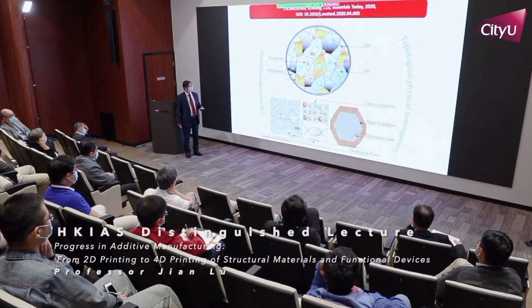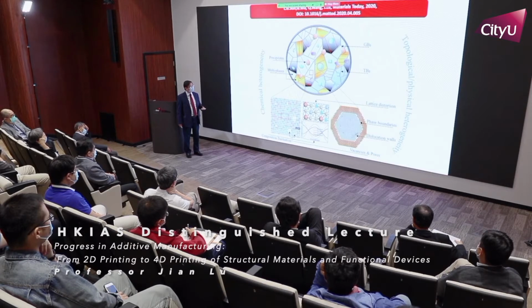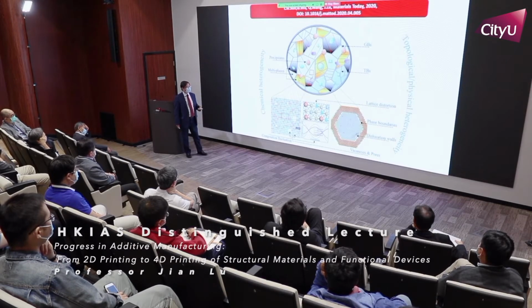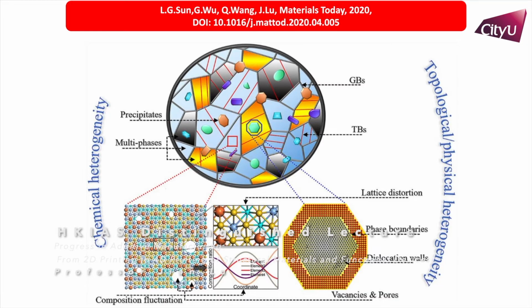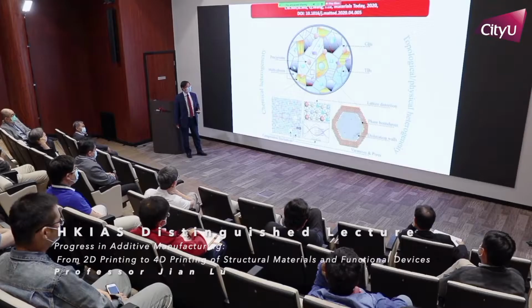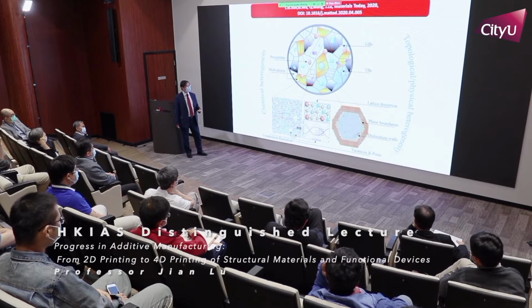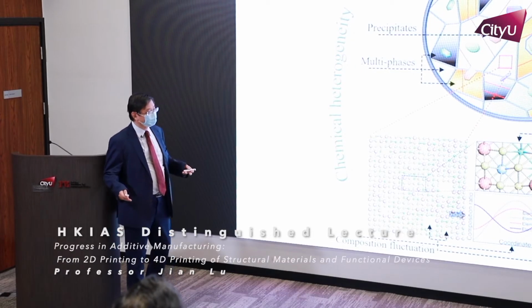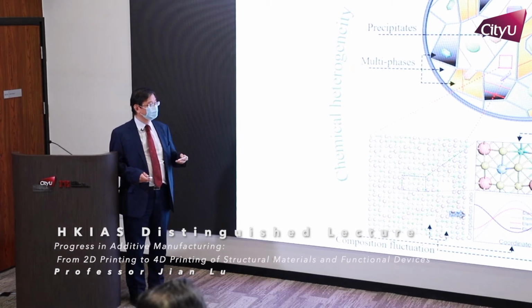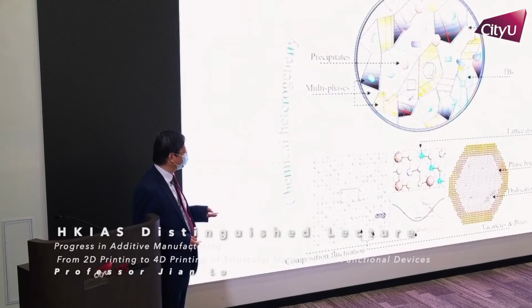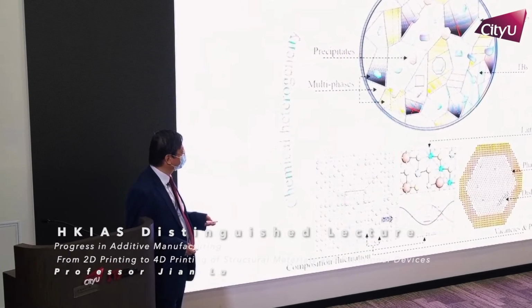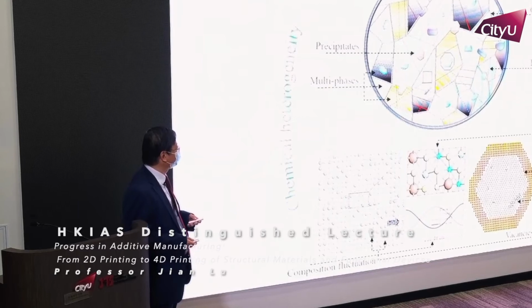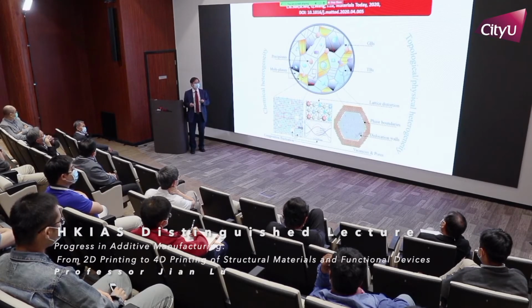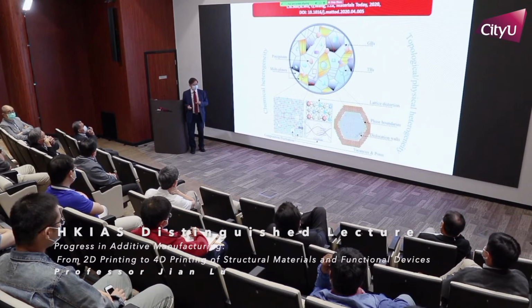So when you insert different material with different atomic size, then locally you generate a lattice distortion for a normal structural material. Of course, we can also have other defects such as vacancy, pores, dislocation, phase boundary. All these can be managed. So we can say today with different tools, manufacturing tools, material processing tools, we can try to manage and organize all this for the final objective of optimized material, component, devices and structure.